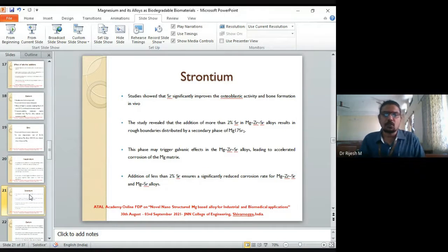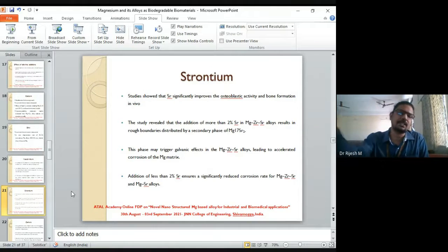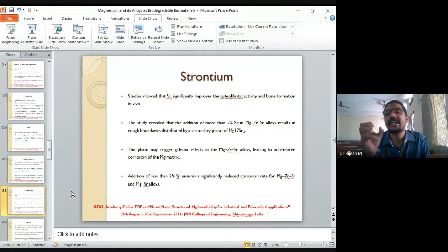Strontium is a well-known grain refiner, if you have studied strontium in engineering applications. What happens is that strontium significantly improves the osteoblastic activity. Osteoblastic activity is nothing but the formation of cells which can heal. So in the presence of strontium, you actually produce cells that can heal the bone. That's what we call osteoblastic activity and bone formation in vivo. So strontium really helps to heal faster.